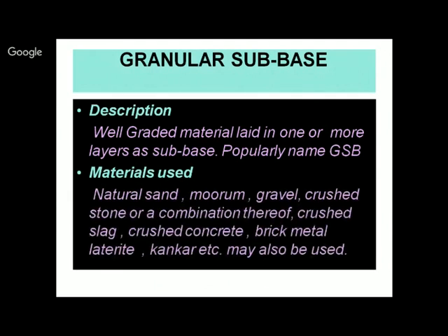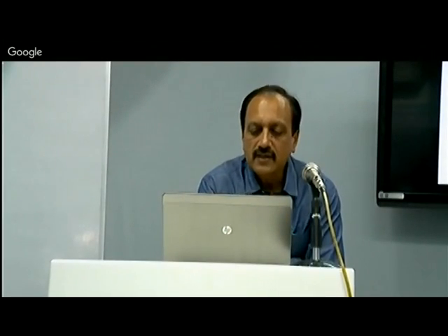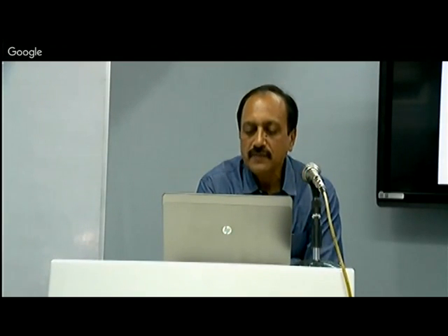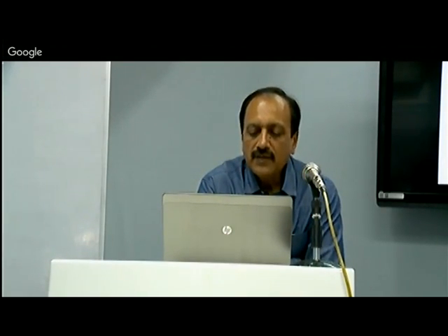We can use natural sand, muram, gravel, crushed stone, or a combination thereof, crushed slag, crushed concrete, brick metal, laterite, and kankar etc. may also be used. Now natural sand alone is really not meeting the grading requirement which we are going to see. So it could be a combination of any two or more materials.